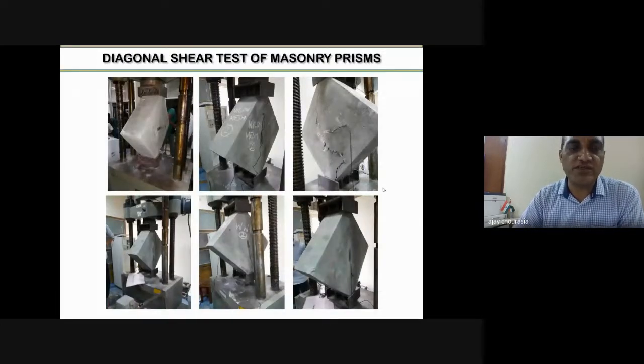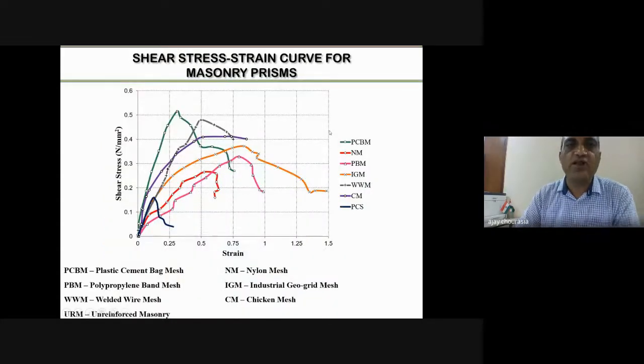Further, the investigation was carried out to assess the shear strength of the masonry by using a protocol given in ASTM E519 by conducting diagonal shear tests on masonry wallets. Again, apart from the control specimen, all these 6 different options were carried out, plastered, and tests were carried out. The response was measured by means of strain gauges and LVDTs, which were provided perpendicular to the direction of the loading. The results were plotted between shear stress and shear strain. The results showed a similar trend as we have seen in the compressive stress, that a substantially good enhancement in shear strength has been noticed in the case of welded wire mesh and plastic cement bag mesh in comparison with the control specimen and other alternative options.